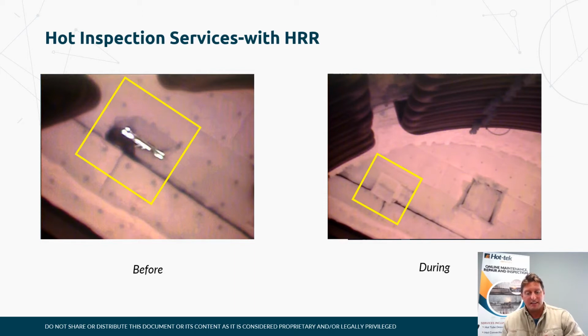And then this is another 2 stills taken during a refractory repair. So as you can see on the left, substantial amount of refractory damage breaching the outer shell as well, so we could see straight to outside from there. And we were utilizing the inspection scope the entire time during this specific application to ensure that we were properly restabilizing very fragile refractory that was surrounding the damaged area.